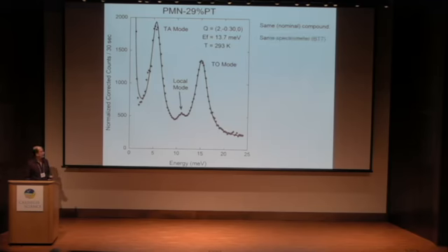It's not 200 grams, but it's fairly large. It was 80 grams. We measured these data on the same triple-axis spectrometer, BT7. And we did it under the same configuration, so roughly the same collimations and roughly the same fixed final energy. So that way our resolution is comparable. And we note that we actually get the same relative intensities as Mike did in his data. So this is the local mode here that is situated between the acoustic mode and the optic mode.